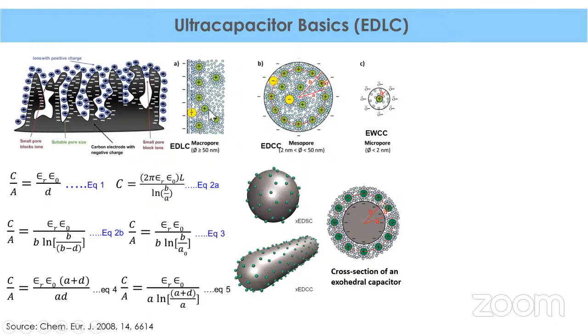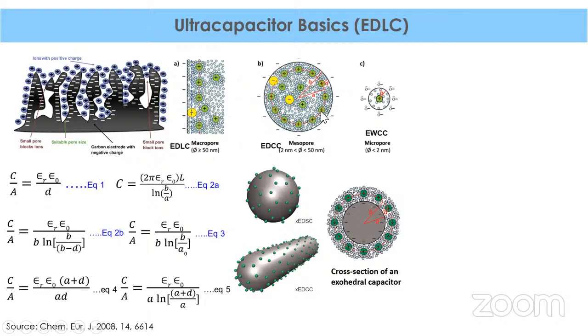All these three kinds of pores have their energy storage capacity explained with different types of mechanisms, and accordingly the equation has been modified to justify the high specific capacitance of ultracapacitor systems. In the case of macropores, because the pore size is above 50 nanometers, the electric double layer is a good approximation for the carbon electrolyte interface. But this equation 1 may not actually reflect the scenario for mesopores and micropores. In nanoporous materials, as I said, pores can be not only cylindrical but also slit and spherical type, depending on the synthesis approach.